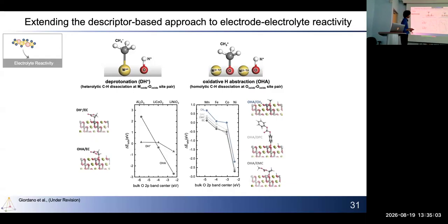What we generally find is that as you change the chemistry, for example from manganese to nickel, your oxygen 2p band comes closer to the Fermi level, and you have more favorable adsorption. So if you're using lithium nickel oxide, which would increase your battery capacity, that generally comes at the cost of increased electrolyte reactivity. So you have this trade-off because these surfaces are generally good at pulling hydrogen from a lot of these electrolyte molecules.